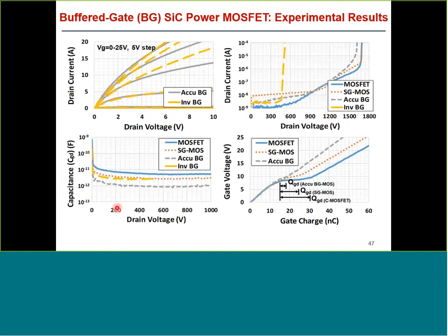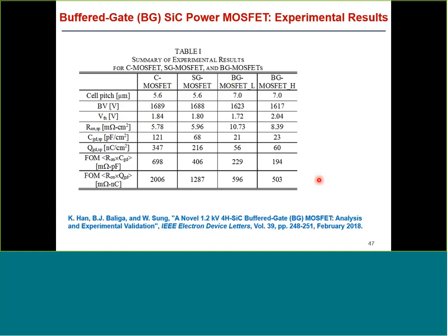In terms of the capacitance, you can see that there is a big improvement in the CGD at high voltages as well as lower voltages by using the BG MOSFET structure. And this improvement, this reduction, translates to a very, very low value of QGD. So this is an exceptionally low value of QGD, which gives us very high figures of merit as shown in this table. So this summarizes all the experimental results for the conventional MOSFET, SG MOSFET, and two types of BG MOSFETs. The BG MOSFET L had a slightly lower doping concentration for the N+ JFET region, and this one had a slightly higher doping concentration.